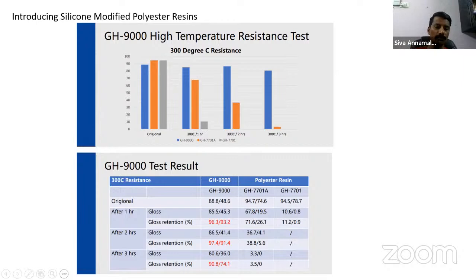Whereas here the gloss from 88.8 comes down gradually. The percentage of gloss retention is above 90%, even after 3 hours of continuous exposure in a glossy finish. What is most important is that it is a glossy finish. It is not like a silicone resin texture finish. It is a glossy finish. Even in a glossy finish, you are getting excellent gloss retention even after longer exposure.